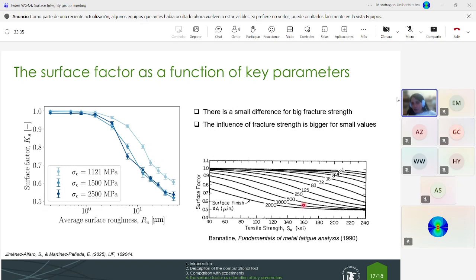This is the same conclusion we can observe here, where you can see that for big values of the tensile strength, there is almost no difference in the value of the surface factor. So we observe similar tendencies, although we are not comparing with the same parameters as I've said before.